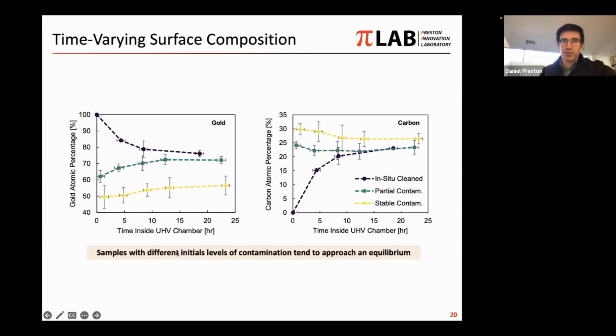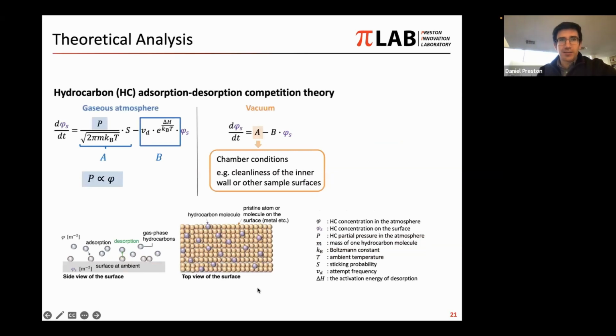And all these approach some sort of equilibrium, which we kind of see from the data here. So we tried to conduct some theoretical analysis to better understand this. We wanted to develop a model that could explain the results that we're seeing. And we did this with some hydrocarbon adsorption-desorption theory on the surface. In a gaseous atmosphere, typically you might model some adsorption based on the molecules hitting the surface, some sticking coefficient, and some desorption maybe based on this spontaneous popping off of particles or molecules from the surface.